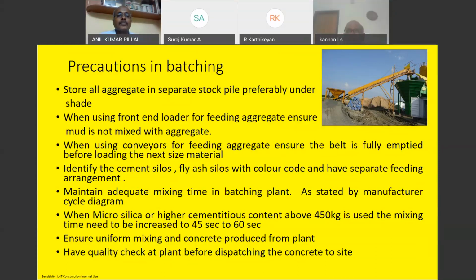Suppose fly ash goes into a cement silo, or cement goes into a fly ash silo, which can create havoc in the system. If cement goes into fly ash, nothing is going to happen. If fly ash goes into cement, unknowingly, finished. You will be assuming that cement is there in the silo, whereas you will be feeding only fly ash. After some time, the purchaser is going to say, my concrete slab is not set. When you investigate, you will find it is full of fly ash. So you have to have the right mechanism to identify the material feeding into the silo so that errors are minimized.